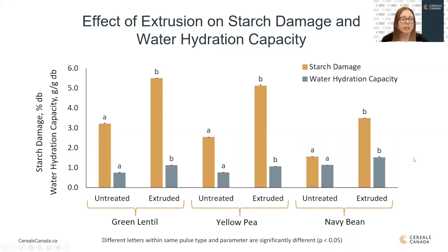So there was an effect on starch damage and water hydration capacity. The extruded flours for each pulse type had a higher starch damage and a higher water hydration capacity. This increase in starch damage was really what we were targeting. We didn't want to have large amounts of starch damage, as we know that that didn't work great in the applications that we were planning for.